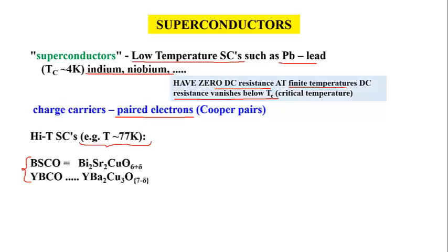These are single crystals, by the way, although they can be made polycrystalline, but they're still crystals. Polycrystalline just means that the crystals are smaller than the typical object, and there's lots of them, but they're fused together so that you have the ability to still have superconductivity. The YBCO, you'll notice, is seven minus delta, so you have to decrease the amount of oxygen to get this to be superconducting.